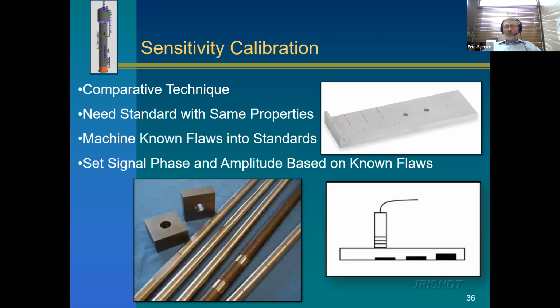With eddy current, there's no absolute calibration. It has to be a comparative technique. It's a comparative calibration. So all we can do for eddy current is we have to have a material that has exactly the same metallurgy, exactly the same heat treat properties, and we machine defects into that material, and then we calibrate our eddy current system based on those artificial defects in a part that has exactly the same geometry, exactly the same metallurgy, and exactly the same heat treatment.